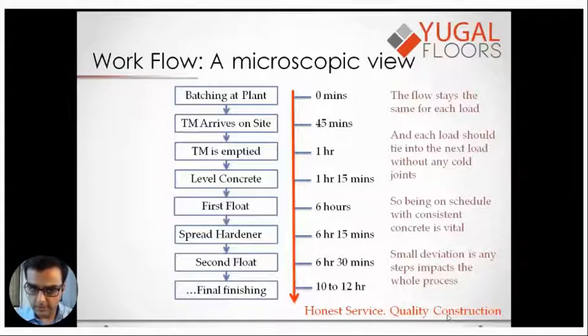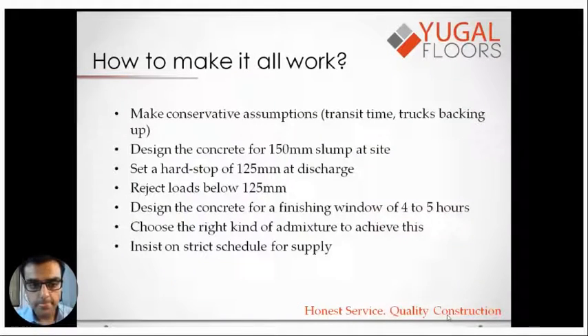Again, when I say consistent concrete, I mean I need similar kind of slump for all the trucks because it affects my finishing drastically if the slump varies from batch to batch. I think it is pretty obvious that small deviation in any step impacts the whole process. Okay, so now I will come to the solution. If I have to make this whole thing work, what should my concrete look like?